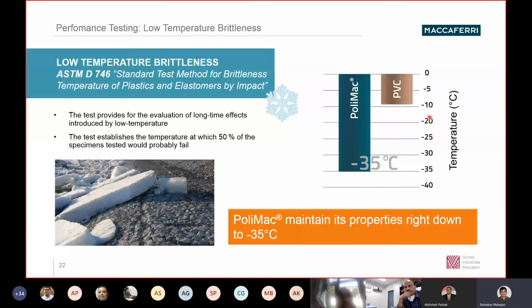Then Polymac maintains its properties when it is subjected to lower temperature. Usually at lower temperature the brittleness comes into the picture, but the ability of Polymac to maintain its properties at such a low temperature is, I would say, better compared to PVC. Usually PVC can maintain its properties up to minus 9 degrees centigrade, whereas this can go to minus 35 degrees centigrade.